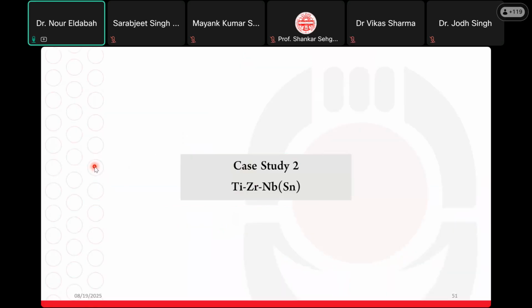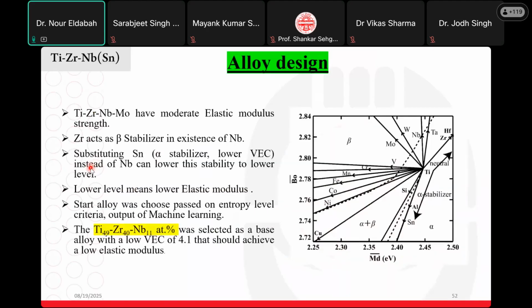Okay, going now to our case study 2. Now we have successfully achieved a low elastic modulus of around 70 gigapascals, but we need to reach a lower elastic modulus. We consider that the base we have is titanium. After we excluded molybdenum, we have titanium 49, zirconium 40, niobium 11, and we look at whether we can destabilize the beta phase a little by adding some alpha stabilizers, and we consult the calculation of phase diagrams about stabilizing the beta phase, so we can achieve a low elastic modulus.